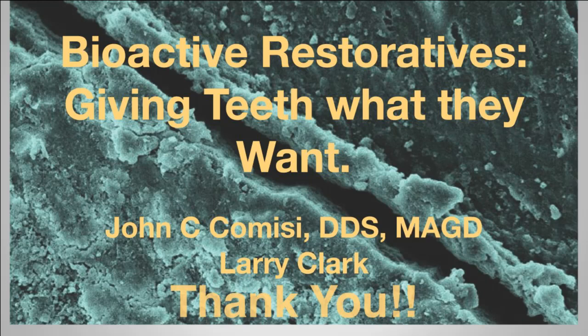And I'd like to say something about that also, because when we first put out our first white paper, we talked about fluoride release, and in that case it was greater than the glass ionomers that were being tested at Tufts Dental School. But that was really a diffusion of ions test. It wasn't just a static test of putting the materials into a beaker and measuring ion release. There was a separation of the ions from distilled water, and so the ions had to actually pass through the material to get to the distilled water and then be measured. So what we're actually saying here is we diffuse more ions. That doesn't mean we have more ions to give.